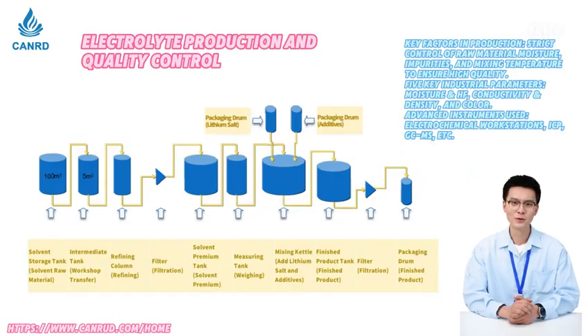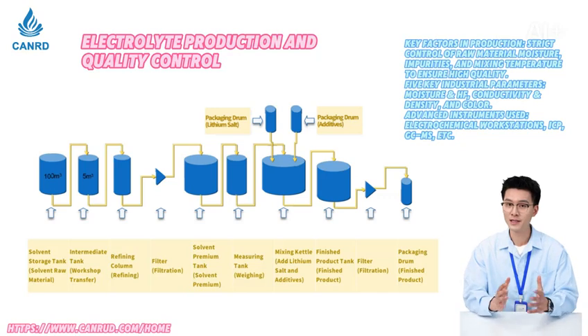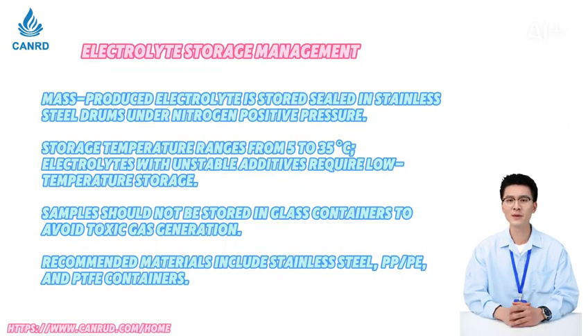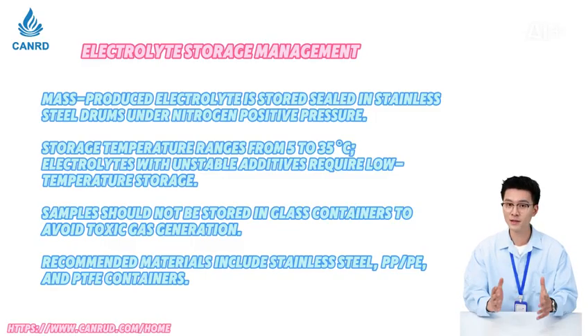Electrolyte quality starts with tight control over raw material moisture, impurities, and mixing temperature. The industry focuses on 5 key parameters: moisture and HF content, conductivity and density, and color. We use electrochemical testers and precision analyzers to ensure every batch is stable and reliable. Mass-produced electrolyte is sealed in stainless steel drums with nitrogen positive pressure, typically stored between 5 and 35 degrees Celsius. Electrolytes containing unstable additives need cold storage. Samples should avoid glass containers because they can produce toxic gases. Stainless steel and polymers like PP and PTFE are preferred.